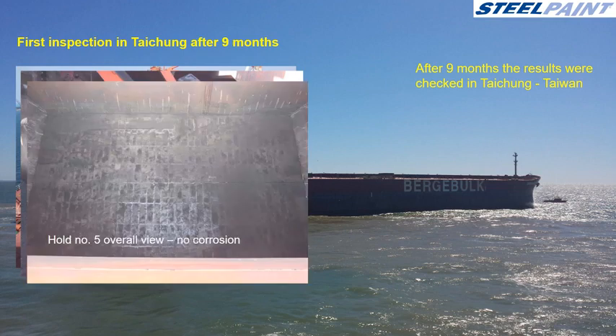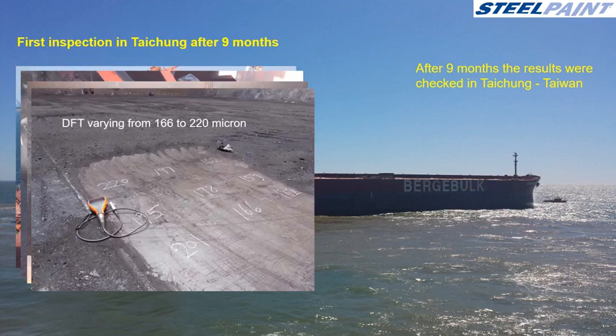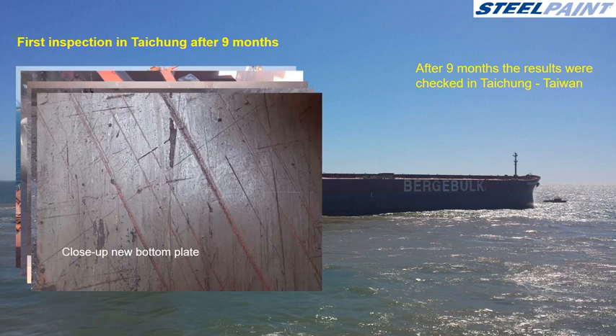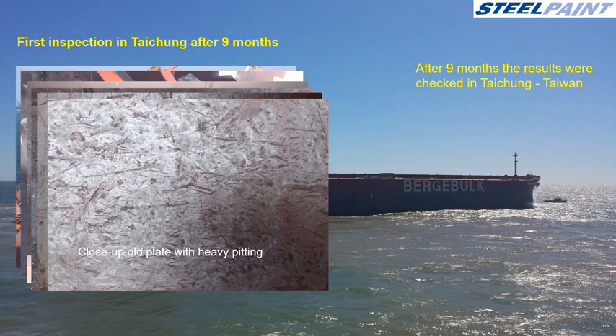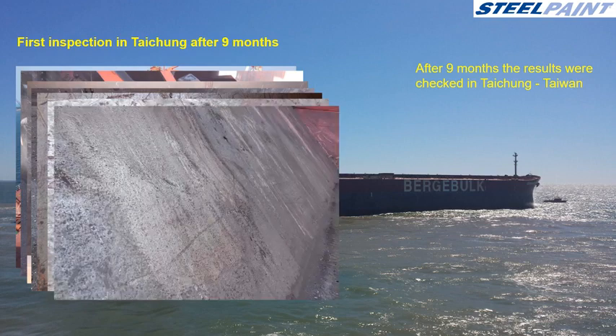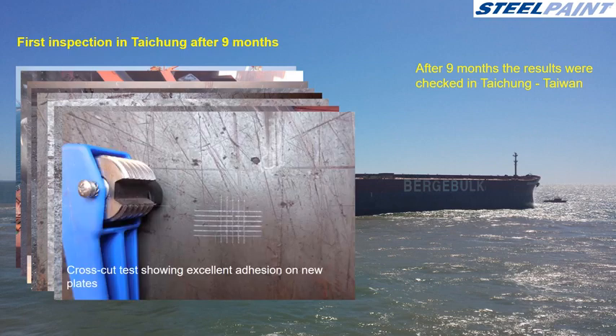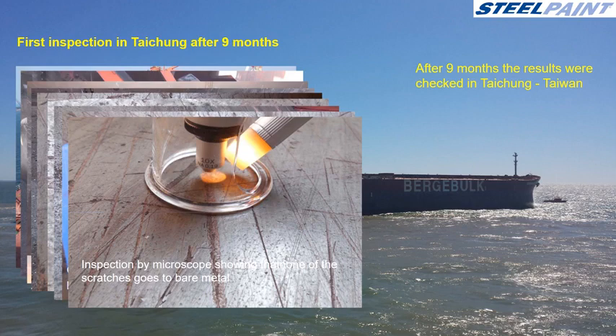This is an overview of hold number 5. No corrosion. DFT varying from 166 to 220 microns. A close-up of a new bottom plate. Close-up of an old plate with heavy pitting. This is a close-up of the lower hopper showing very few damages. A cross-cut test showing that the adhesion is still excellent. Inspection by microscope showing that not one of these scratches goes to bare metal.